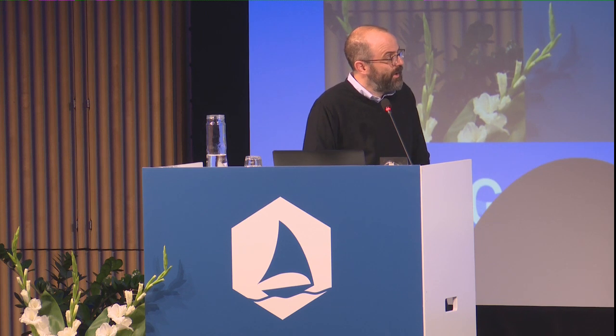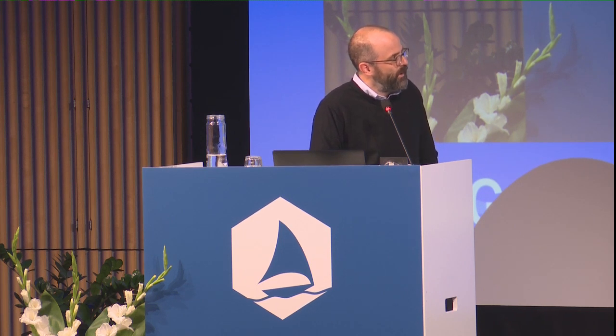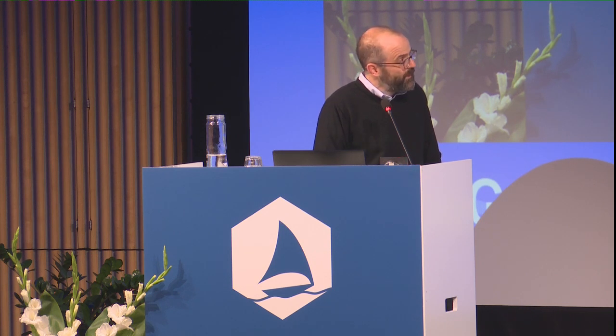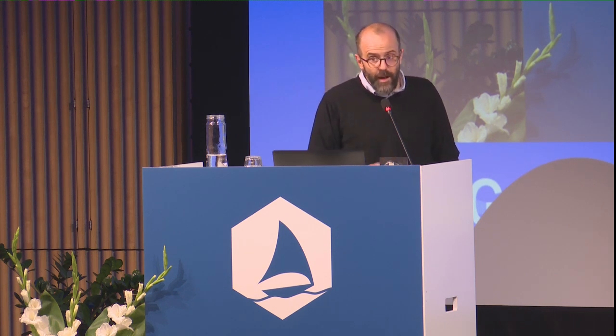application of pressure. And for this talk, the thing I just want you to focus on here is the charge neutrality point. So at ambient pressure, we have a peak resistance that's about 20 kiloohms or so. And as we apply pressure, this peak resistance increases, this is a log scale, by as much as 100 kiloohms. So we're doing something.